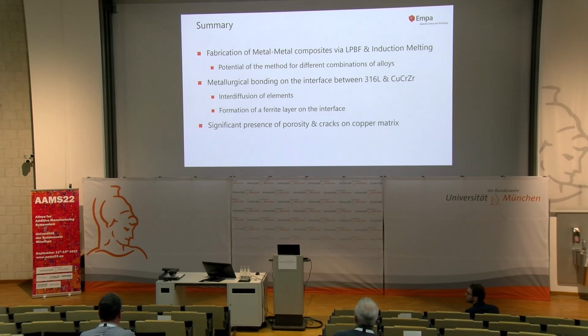and the copper part. We also see the appearance of this ferritic layer with a width of 50 micrometers. This is something that we should pay attention to, in how to thermodynamically analyze the appearance of this ferritic layer. We have the appearance of porosity and cracks, and this is the reason that we will develop more complicated heating cycles, maybe introducing a first heating step of sintering in order to get rid of this porosity, because this is the critical step that should be overcome in order later on to assess the mechanical performance of the structures.